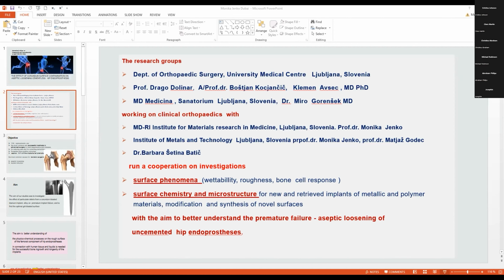And then we tried to prepare our own sample at Ferro-Titanit, a world-known producer of these devices for industry, and here we get the same results. And there are XPS and time-of-flight SIMS analyses of this oxide film.